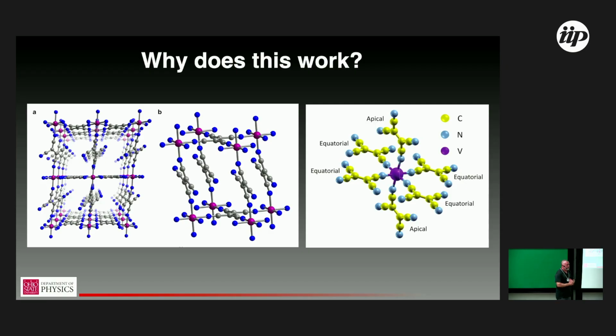And when I went to give this seminar in front of physics audiences, I would get this question a lot. Why does this work? This should not work. For many reasons, but I think the one that people working with solid-state magnetism are primarily concerned with is there's an enormously long distance between vanadium spins, according to most common heuristics of what makes a good magnet. Right, so that's 6 atoms between vanadium to vanadium if you walk your way through the TCNE molecule. And it's not unheard of to have magnetic interactions over that distance. It's shocking to have a 600 Kelvin ordering temperature with spins that are that far removed.